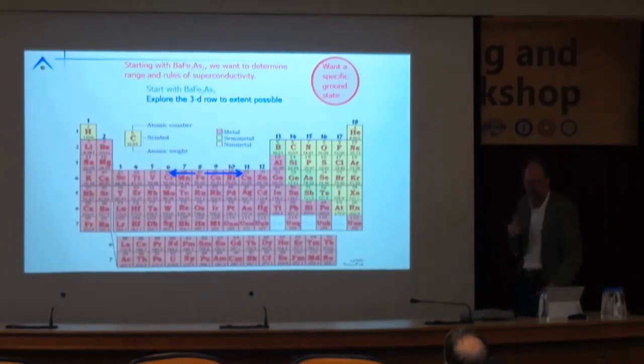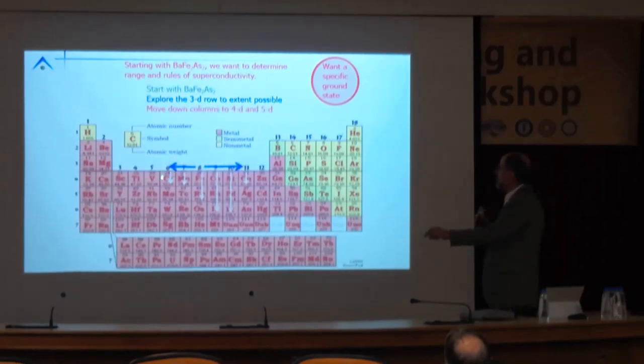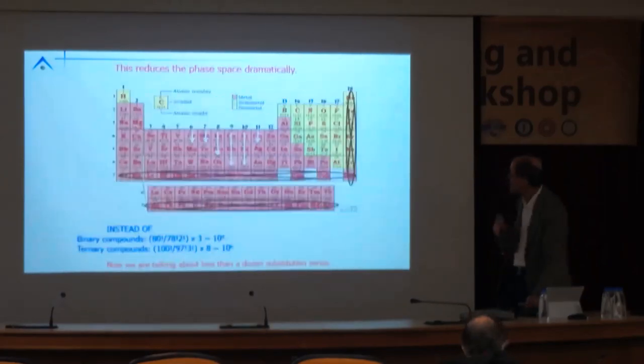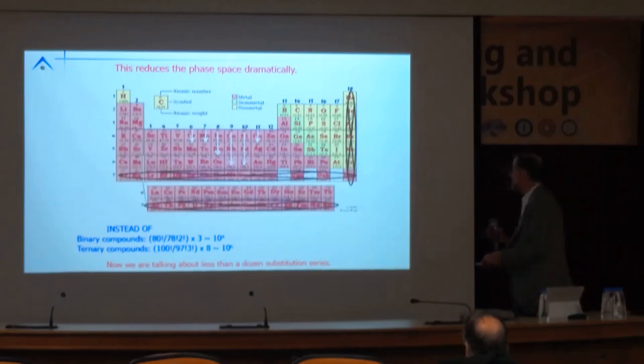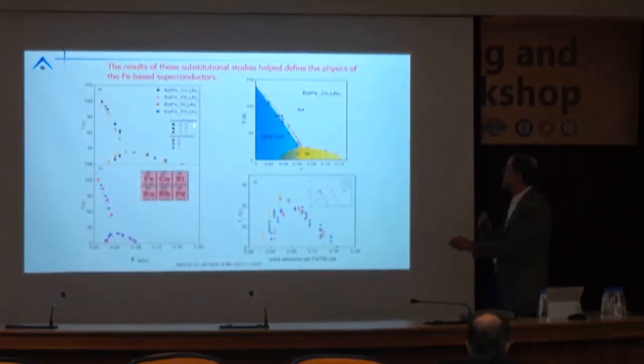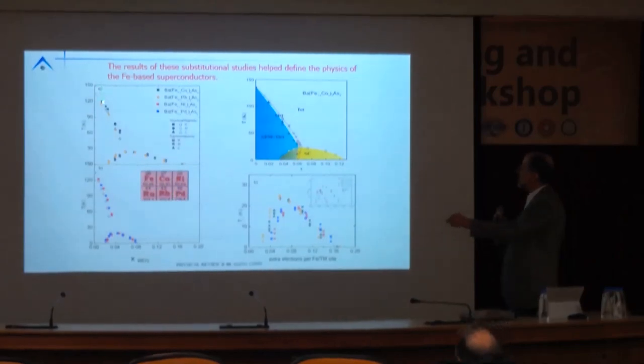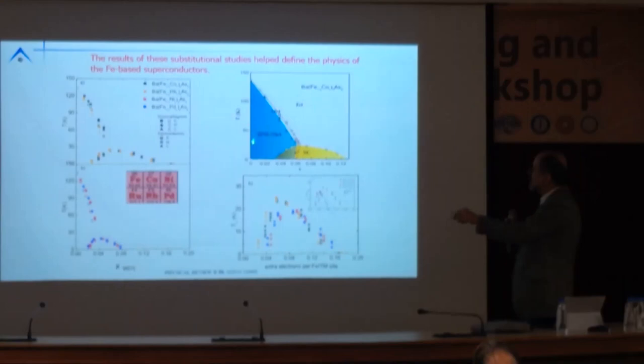This led to a desire to generalize and to understand this more clearly. So what you can do is you can look at the various 3d, you can move down to 4d and 5d as you will, and instead of having, you know, your blind combinatorial millions of compounds, we're talking less than a dozen substitution series. With this, we look at a subset of just looking at cobalt, rhodium, nickel, palladium. With cobalt and rhodium, we have exactly the same phase diagram. We suppress the orthorhombic antiferromagnetic transitions, split it a little, see a dome of superconductivity existing both under the antiferromagnetic orthorhombic and outside of it, with a maximum near what might be a quantum critical point.